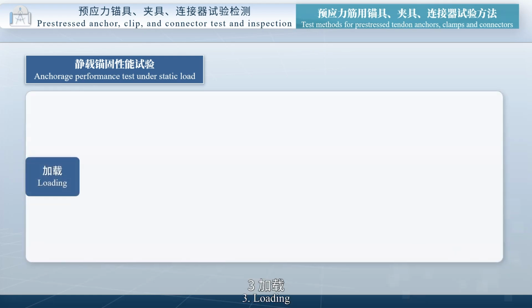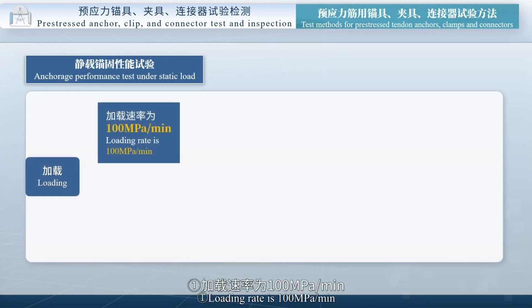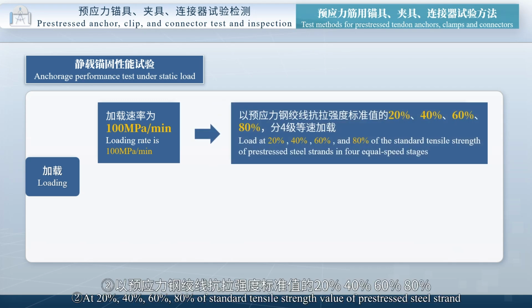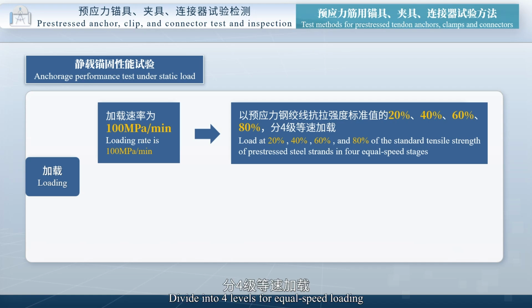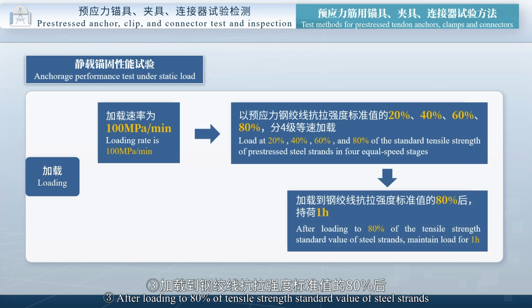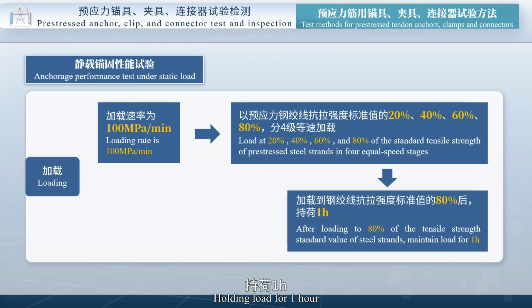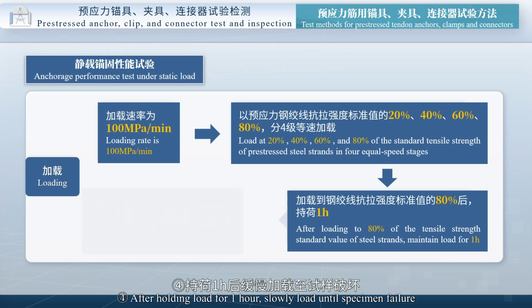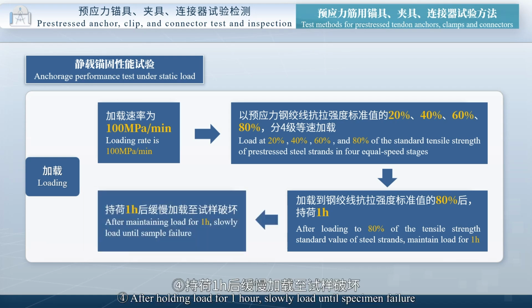Third, loading. First, the loading rate is 100 megapascals/min. Second, at 20%, 40%, 60%, 80% of the standard tensile strength value of the pre-stressed steel strand, divide into 4 levels for equal speed loading. After loading to 80% of the tensile strength standard value of the steel strands, hold the load for 1 hour. After holding for 1 hour, slowly load until specimen failure.